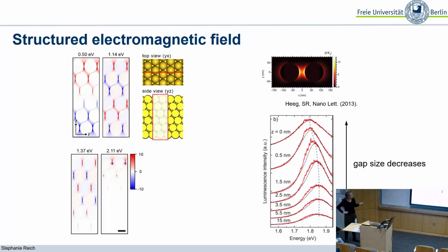The white parts is where the gold nanoparticles are, but this is really the outcome of the simulation. We did not put them to zero, they are white because there is no electric field inside the matter. And we thought, okay, so this is a nice system to use in order to place something in this hotspot and use it to increase optical processes.